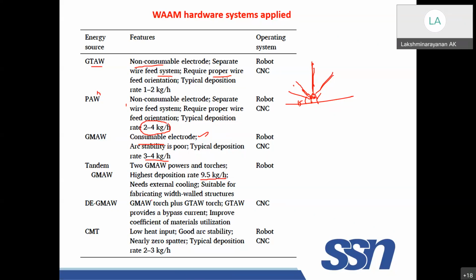Okay, as in one of the pictures I showed, you can use a combination of GMAW and GTAW, where the GTAW provides a bypass current, and material utilization, how it is being melted, will be improved. Okay, CMT, as I mentioned, is a low heat input process, because the wire is retracted once the droplet forms. So further heating is not there for this liquid metal. So this is a low heat input process compared to the GMAW process. Good arc stability is there, almost zero spatter. The deposition rate is around 2 to 3 kilograms per hour.